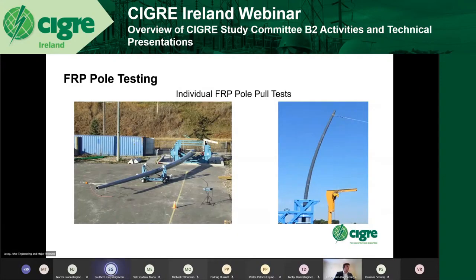So as the dramatic image on the left illustrates, they do bend. But probably looking at the large displacement in this doesn't give the whole picture, because if you did a similar test with a wood pole, you would find that the displacement would be the same, or even the composite is probably slightly stiffer, just ever so slightly stiffer. The poles are obviously benchmarked off wood poles, so the properties that the suppliers try to get out of the poles are benchmarked off the wood poles, so you would expect a similar performance from a deflection test.